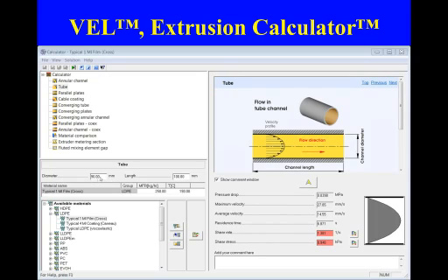We have a 90 millimeter diameter tube, basically, with, I just picked, a length of 100 millimeters, 250 kilos per hour, and 190 degrees Celsius. And I'm using a 1 MI film material. And when you perform that calculation, over here we have the flow characteristics of that particular flow field. And we can see that our shear stress is showing at 8.9 kilopascals.